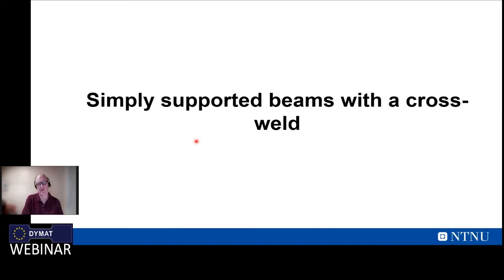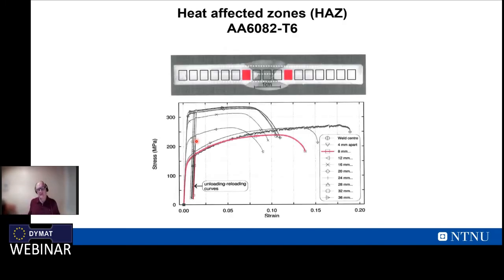If we now introduce a cross weld, then we have a challenge, and this is something that people do not know. If you have two plates which are welded together, you have a weld, you see here, but you have a heat affected zone. And if you take this stress strain curve, which is obtained from a small specimen out here, then you have a stress-strain curve like this. But as you move towards the weld, you see that you lower the yield stress and you change the hardening. And you see that in the heat affected zone close to the weld, you have a curve like this.